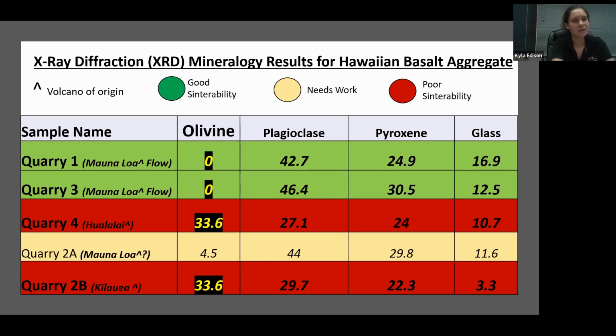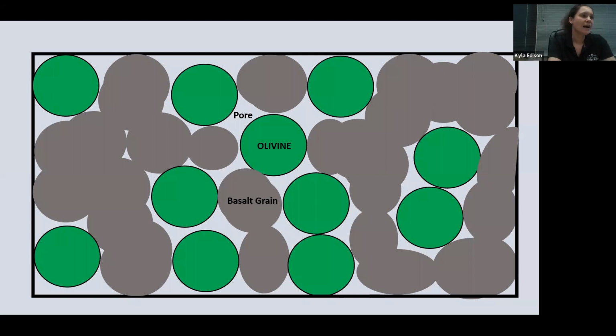They have very high plagioclase and a fair amount of pyroxene and a fair amount of glass. But if you look at Quarry 4, it has 33.6% olivine, which is really high compared to Quarry 1 and Quarry 3. And so it started to make sense that maybe olivine is the true culprit for a very bad material.